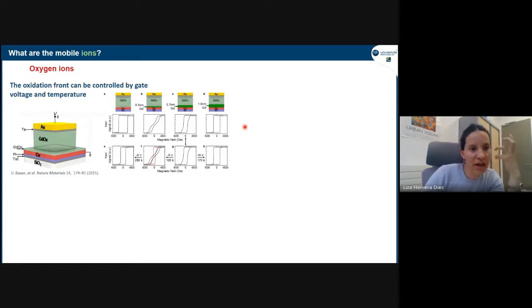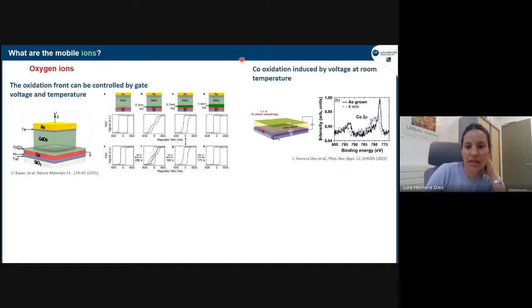So then they said, well, if we're actually oxidizing the system with a voltage, then we should be able to see these changes that we did on purpose, growing the system ourselves. We should be able to see the system going back and forth between all this with the action of a gate voltage. And this is really what they saw. They took this film and applied positive or negative voltages, and they could really go through all these different states, and they could propose that there was a front of oxidation from the gadolinium oxide that would come down to the cobalt interface and back out, depending on the sign of the voltage applied. So this is the oxidation.